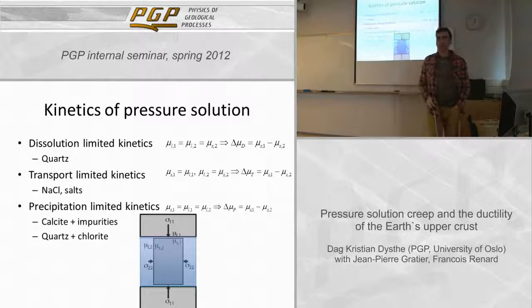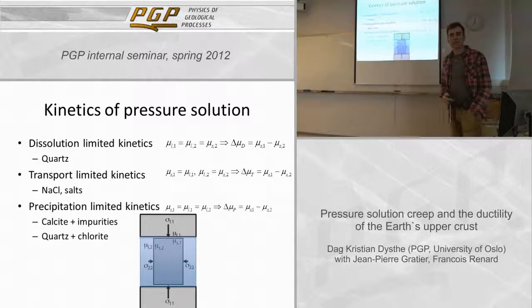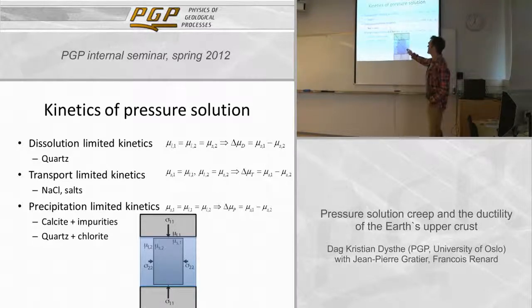For salts like sodium chloride, sodium chlorate, that we like to use in the lab for experiments, and also maybe in some situations for gypsum and calcite and other materials in the Earth's crust, what is limiting the rate of the whole process is the diffusion out through this thin liquid layer. In this case, as before, you will quickly equilibrate these two chemical potentials and these two, and the driving force is the total driving force.